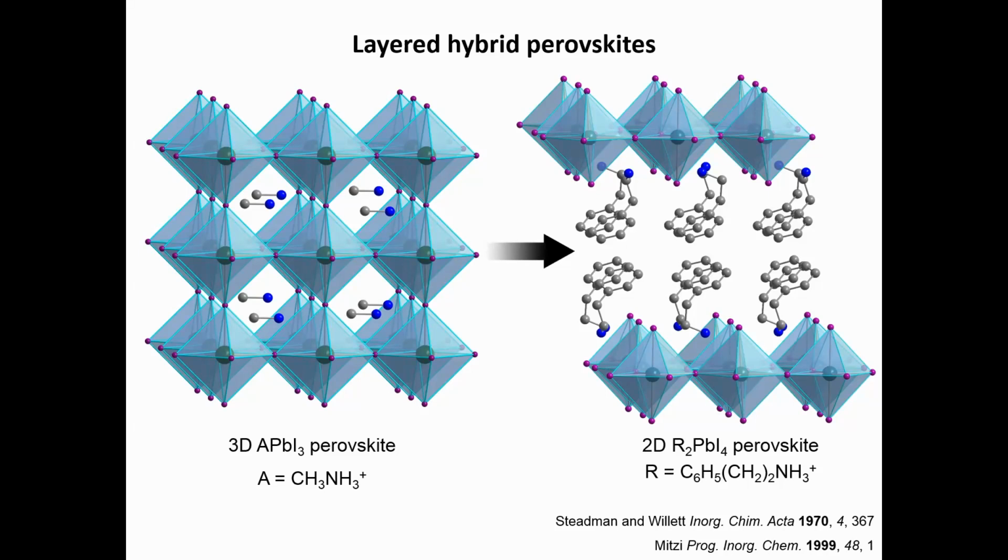The only way we can kill the emission is if we start throwing in impurities. There are certain impurities where the excitations funnel to that impurity and it quenches the emission. But if we don't change the composition, we haven't been able to change the emission through crystallization methods.